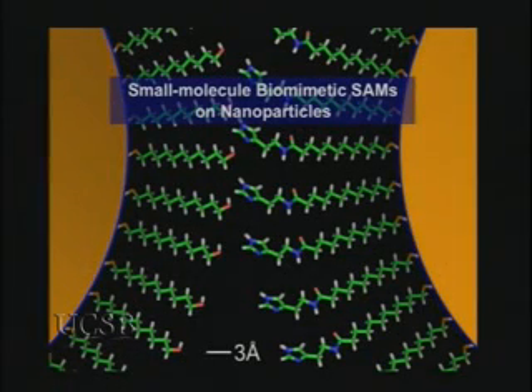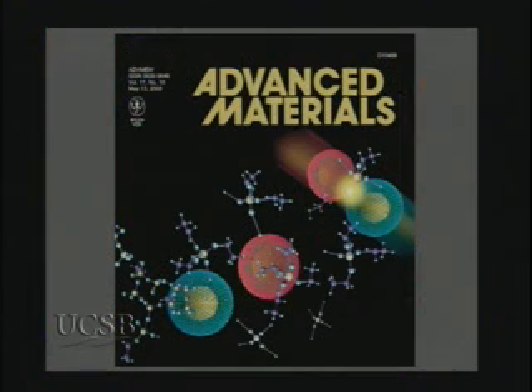Taking this a step further, getting away from the requirement for polymers, if we make self-assembled monolayers, take small molecules with those same functional groups that we identified by genetic engineering as required for the catalytic reaction in the protein, and anchor them onto, in this case, gold nanoparticles, we found that just as in the enzyme, in the protein, it's the interface between those 2 different groups that is required for catalysis. Either alone is inactive, and if we make substitutions, just like in the genetic engineering, we knock out the catalytic activity.